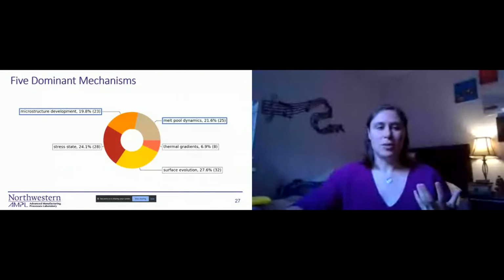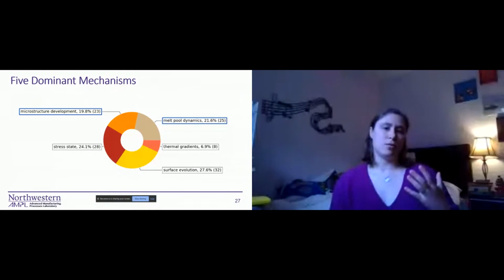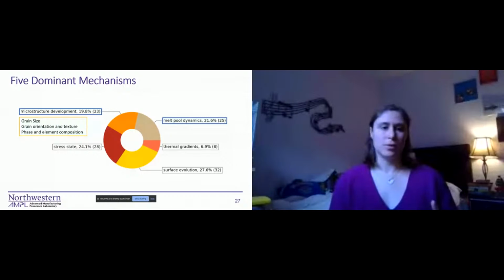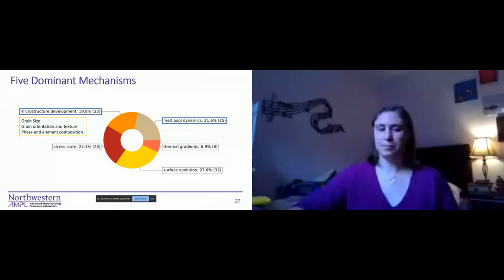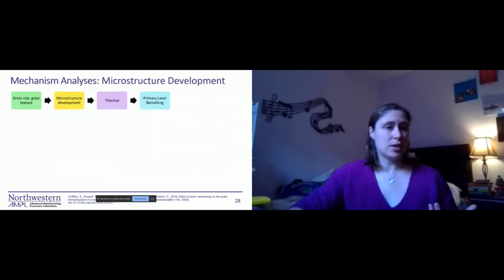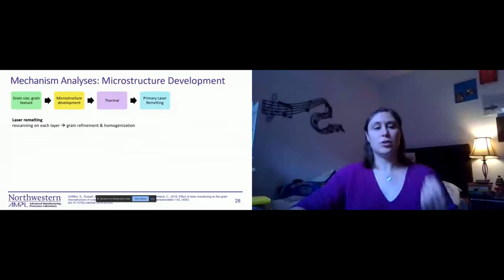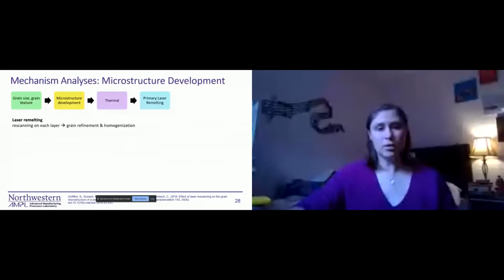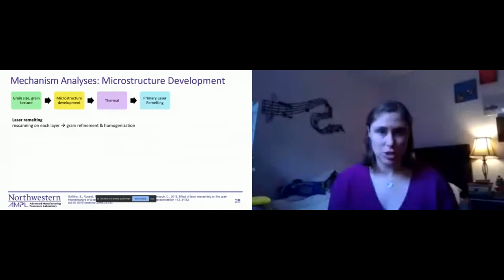Going back, and now I'll be speaking about microstructure development, where we can look at effects on grain size, the grain orientation and texture, as well as phase and element composition. So looking at grain size and grain texture, using a thermal energy source through primary laser remelting, where laser remelting was performed on each layer. This led to grain refinement and homogenization.